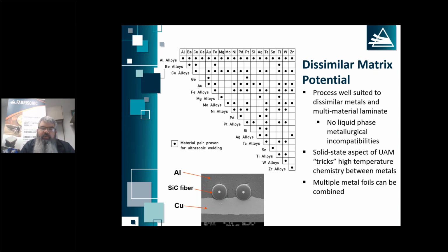So anytime we're working with some sort of non-metallic, we're going to embed that. And when I mean embed it, these fibers were actually just laid on top of the copper and we welded an aluminum layer on top. And you can see we've extruded metal all around those fibers. Under a high power ultrasonic field, metal flows very easily, so we can extrude metal around things that we're embedding.